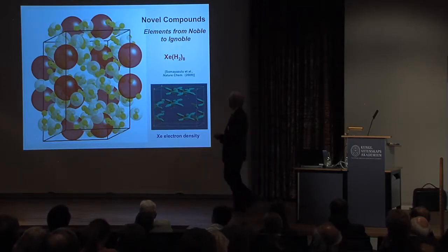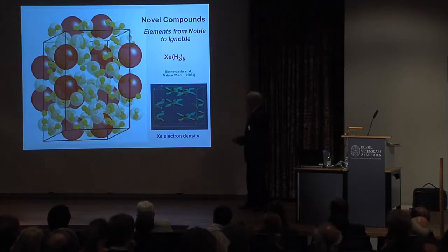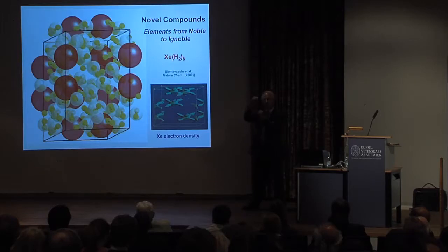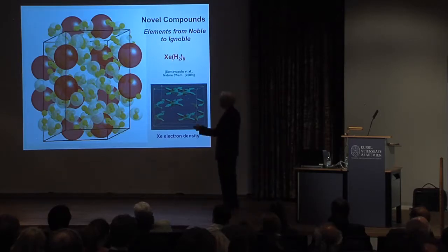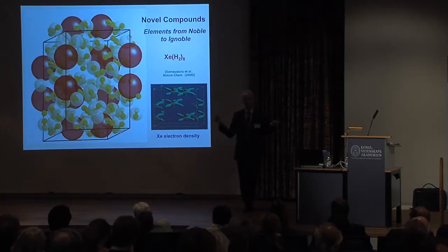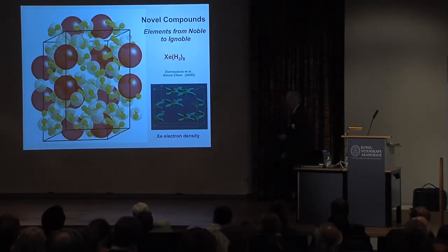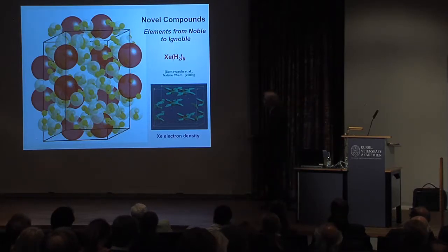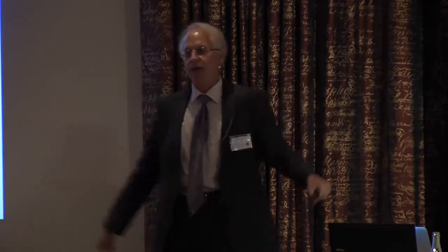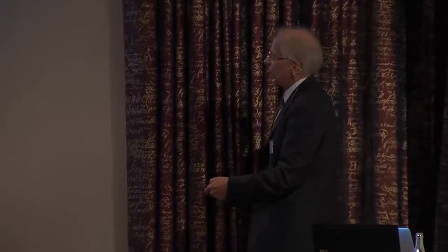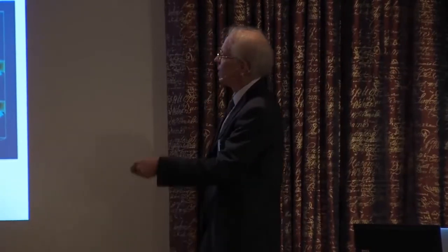Let's take the inert gases, for example, xenon. It's been found that xenon combines with hydrogen to form this structure here. It's a beautiful structure with dimers of xenon atoms suspended in what looks like a lattice gas of hydrogen molecules that are rotationally disordered. If one does X-ray diffraction, one can pull out the electron density. With increasing pressure, you see the bleeding out of charge away from the xenons as the xenons try to reach out and bond into the surrounding hydrogen lattice structure. So really, a very surprising result, a complex structure consisting of these xenon dimers.